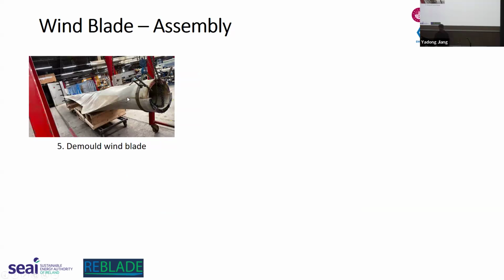So we demolded it, took it out of the mold, and then we wheeled it into the oven in the background. So we have a 16-meter gas fired oven, so we can cure out of autoclave quite large structures. And 14-meter blades is actually the largest we've cured in there.